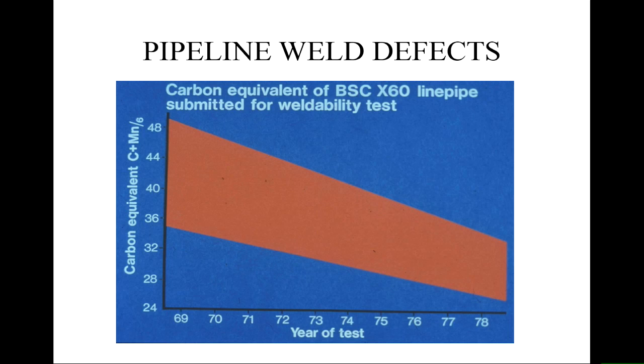Over the years, we have achieved more and more weldable constructional steels by actually reducing the amount of carbon, and in particular the amount of carbon and manganese, in the steels. So you can look at that in terms of carbon equivalent here, which is carbon plus manganese divided by 6. We'll talk later on about different carbon equivalent equations. But basically, to stop forming brittle phases like martensite, we want to effectively reduce the carbon content and the alloying element content of the steels to make them more weldable.